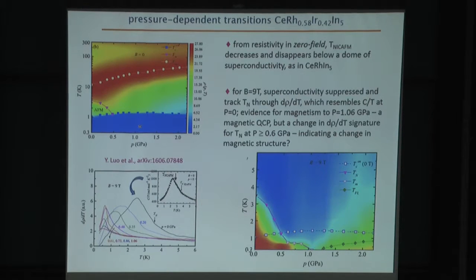Okay. So let's just begin with electrical resistivity measurements. So from electrical resistivity measurements, we've studied the response of this sample to applied pressure, this sample with 42% iridium, and the results are summarized in this temperature pressure phase diagram. So the point I want to make here is that these resistance measurements show that the antiferromagnetic transition, the highest antiferromagnetic transition, is rapidly suppressed with increasing pressure. And above a pressure of about a half a GPa or so, any evidence for this antiferromagnetic order disappears in this superconducting state, basically. We just can't find any evidence for it.